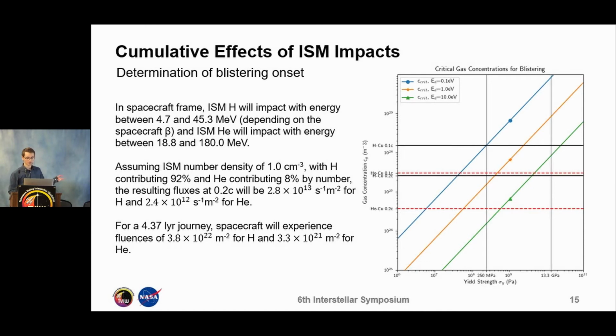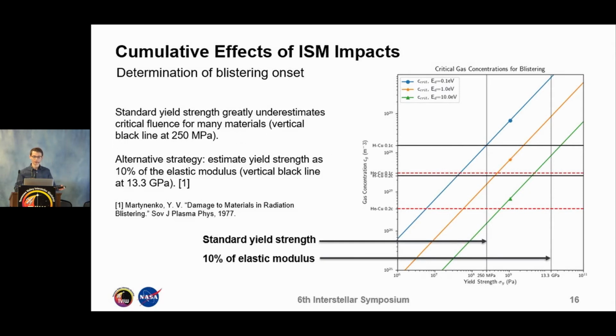Now, this plot shows the critical concentrations of implanted gas atoms for a range of dissolution energies. It assumes a constant ISM number density of 1 per cubic centimeter, and it suggests that materials with yield strengths in excess of 10 gigapascals will not blister. In general, it's difficult to determine the appropriate yield strength to mitigate blistering, because the standard yield strength greatly underestimates the critical fluence for many materials, and this is shown by the left black line at 250 megapascals.